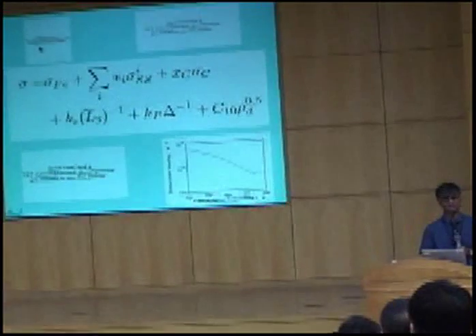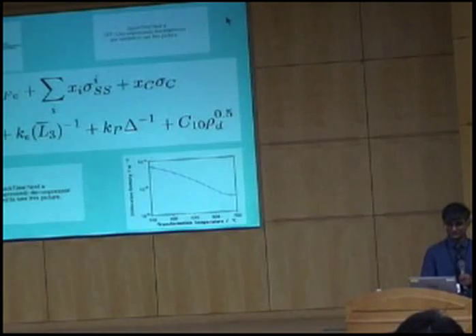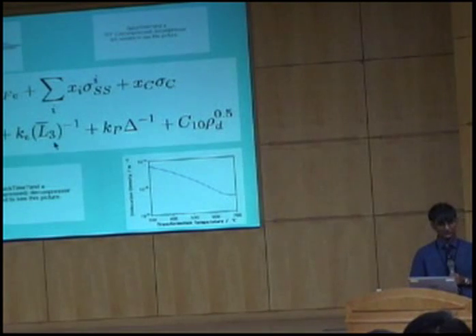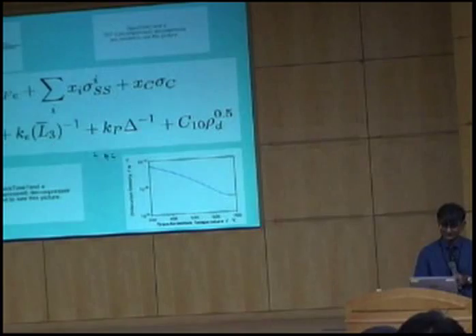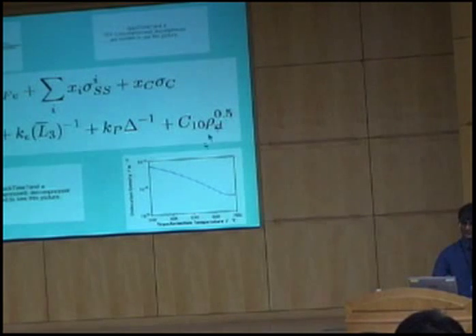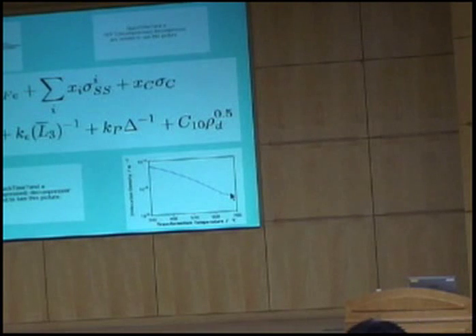Okay, so we go back to this diagram, and you know, we've lost the crystal structure of iron, and this is the dislocation density, but don't worry. We still have the basic equation in mind that the strength consists of the strength of pure iron, solid solution strengthening components, where the carbon behaves in a special way. We have a grain size dependence, which is one upon the thickness of the plates, precipitation hardening, and dislocation density contribution. And by analyzing a lot of data in the literature on dislocation densities, you can simply take this curve to show how the dislocation density changes with the transformation temperature. So that provides you with information on how to calculate the dislocation density contribution.